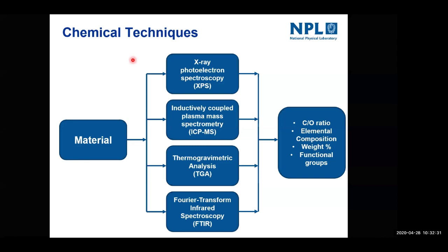Again, it's a reasonably expensive technique. It's done under a vacuum. You're essentially bombarding the surface with X-rays and looking at the photoelectrons that come out to understand the chemistry of the sample, and it is surface sensitive, but it tends to be a very go-to technique for understanding the chemistry of these materials. And so you get an understanding of the elemental composition. If you're doing the XPS correctly and calibrating it correctly, you can get very quantitative information. It also is very good at determining the carbon to oxygen ratio, which is a key measurand to determine the difference between, say, graphene and graphene oxide.